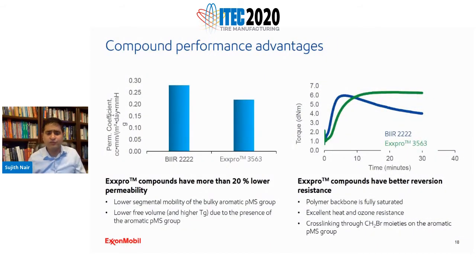So going into the first and foremost important property that we think, as far as Innerliner is concerned, it's the permeability. As you can see, Exxpro 3563 has a 20% improved permeability over bromobutyl. That's one of the key points that differentiates Exxpro from bromobutyl: this lower permeability. And as I said, the reason for this lower permeability is the lower segmental mobility of this bulky aromatic PMS group and the lower free volume, so increase in Tg. Both of those things combined help you reduce the permeability significantly.